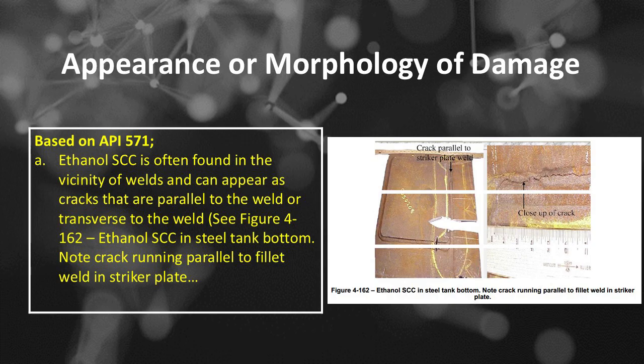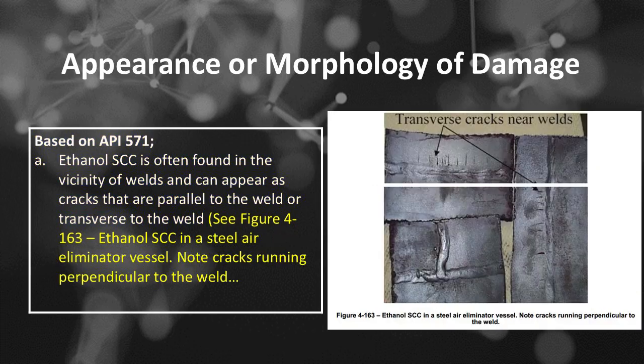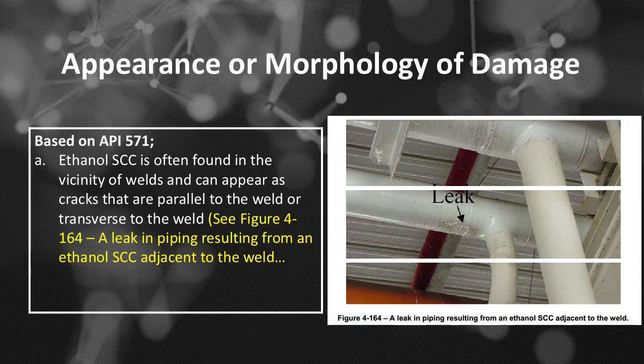Number A, ethanol SCC is often found in the vicinity of welds and can appear as cracks that are parallel to the weld or transverse to the weld. See Figure 4-162, ethanol SCC in steel tank bottom. Note crack running parallel to fillet weld and striker plate. See Figure 4-163, ethanol SCC in a steel air eliminator vessel. Note cracks running perpendicular to the weld. See Figure 4-164, a leak in piping resulting from an ethanol SCC adjacent to the weld.